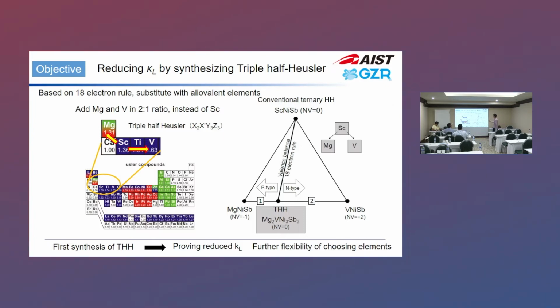The idea is that we had 17 and 19 electrons, but this time 17 plus 20 electrons can be mixed in a 2-to-1 ratio, so that we achieve an 18 electron balance. In this case, the scandium nickel antimony Half-Heusler: the scandium position is split into magnesium and vanadium, and if you mix them in a 2-to-1 ratio, you can design the triple Half-Heusler composition. So the nickel and antimony are now 3. If this compound has an ordered unit cell, you can have an even larger unit cell, and you can get low thermal conductivity again. So it might be worth trying to synthesize it.